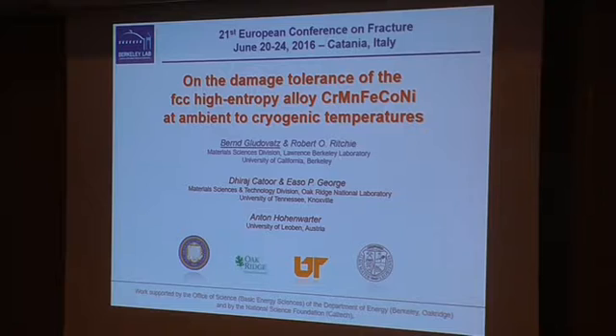At this point, when Easo presented these results at a DOE meeting in Washington a few years ago, my boss Rob Ritchie got curious about this material, so we decided to collaborate with Easo George. We have decided to do our tests and look at samples that contain a crack, on samples that had a grain size of about 6 microns, simply because we can keep our samples a little smaller and still be valid. So Easo processed the material to 6 microns.